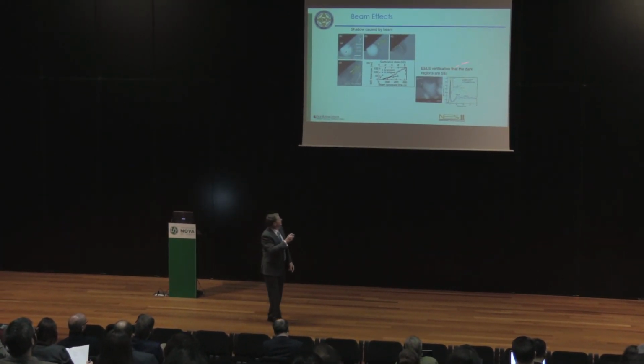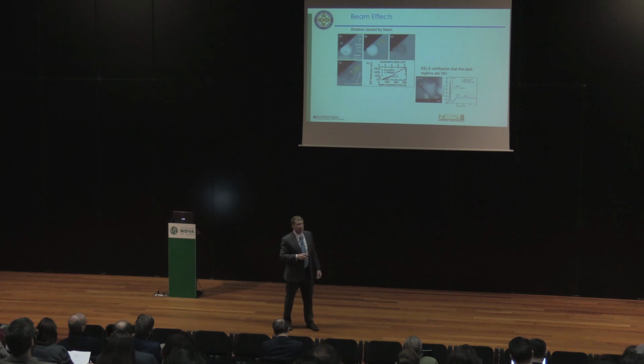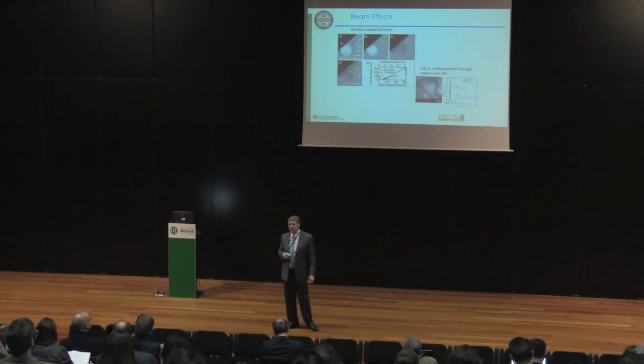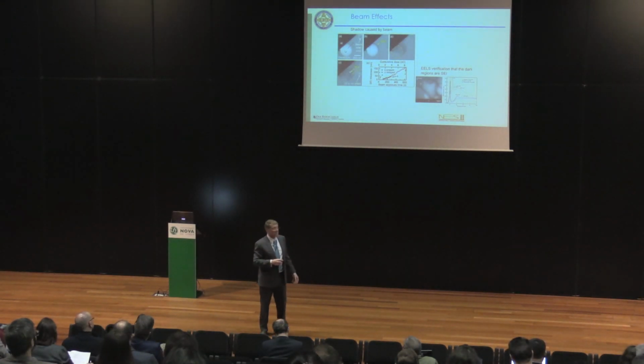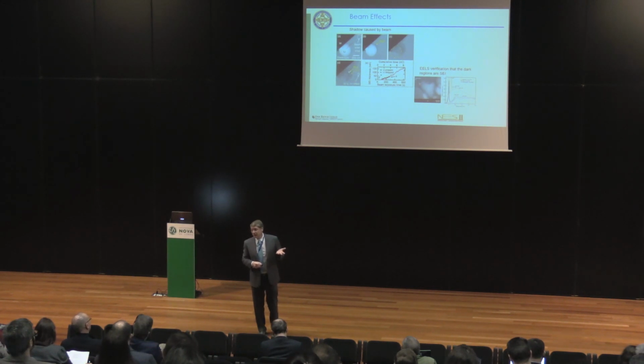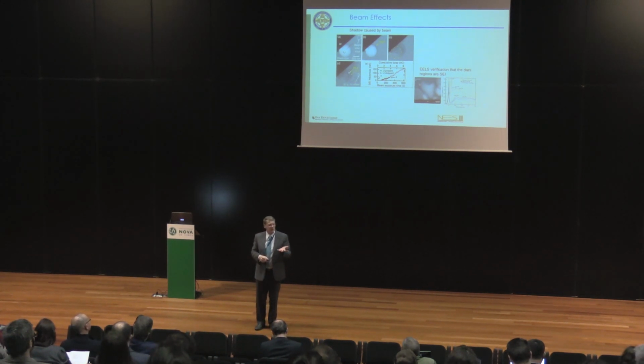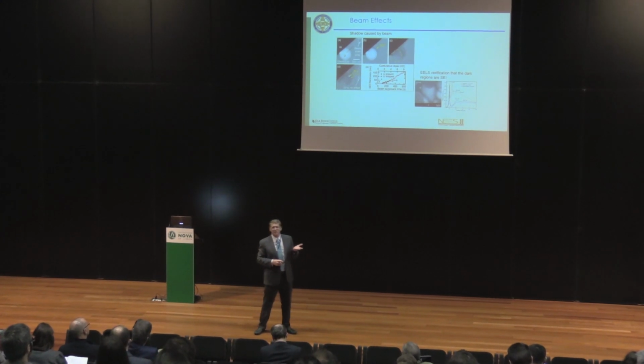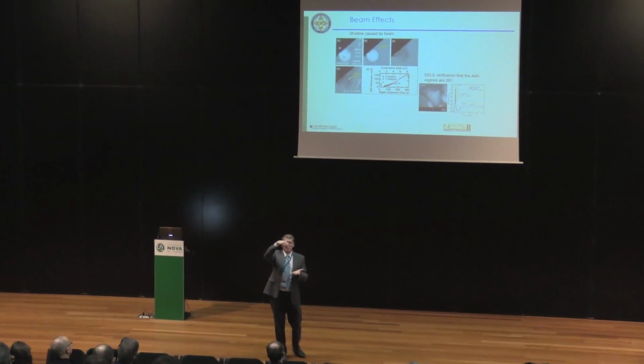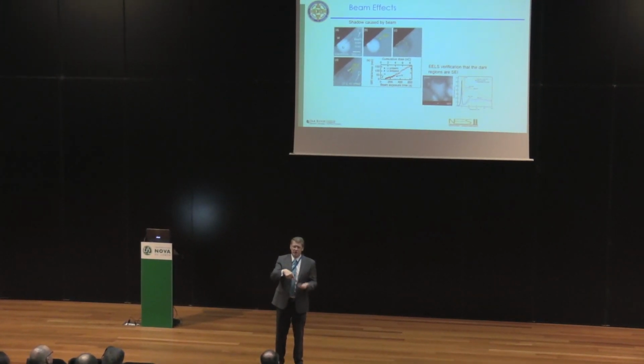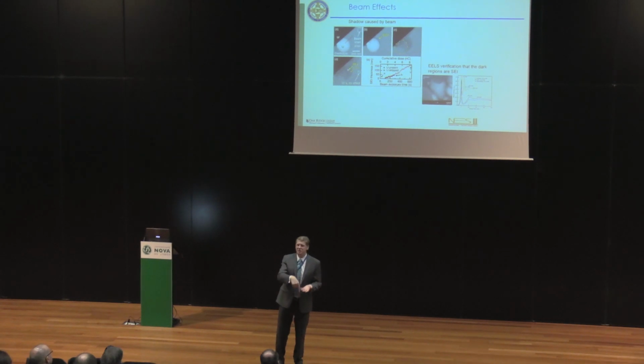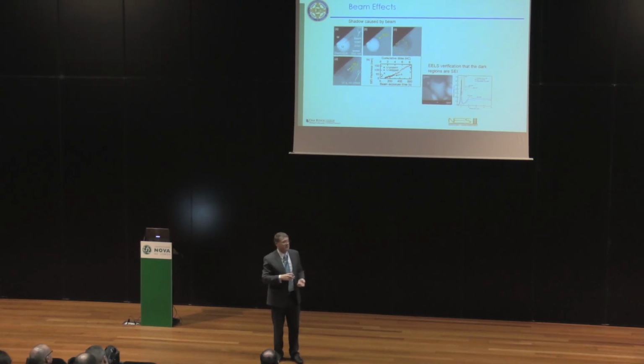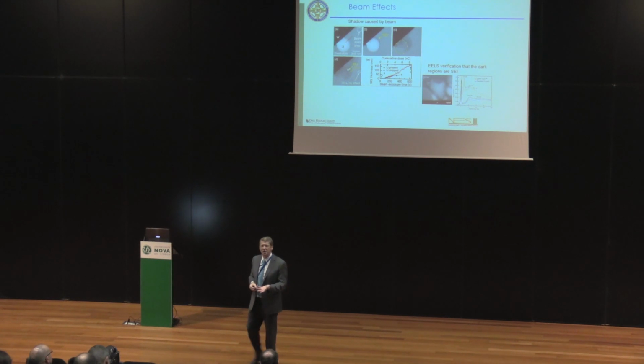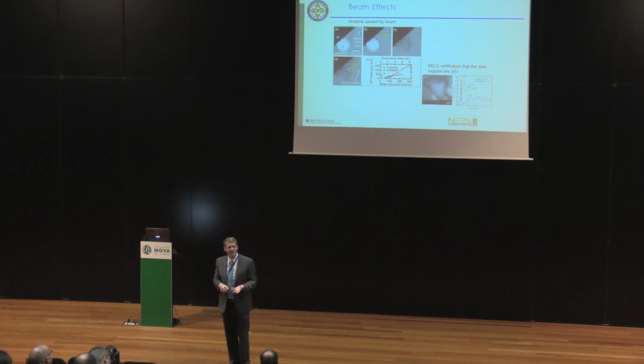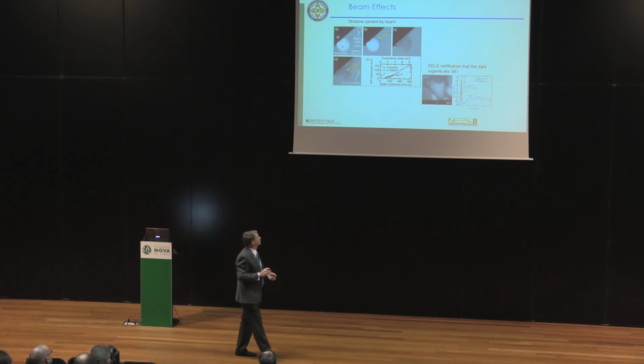Now they did EELS measurements to actually look at this, and so this is electron energy loss spectroscopy. If you're not familiar with it, electron energy loss spectroscopy is when, as you have the electron moving through the system, you measure the change in energy that it has at a given point. It's a Z contrast measurement technique, so you can look at what the atomic mass is in the different areas.